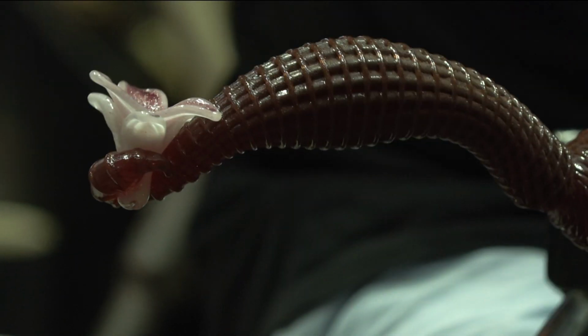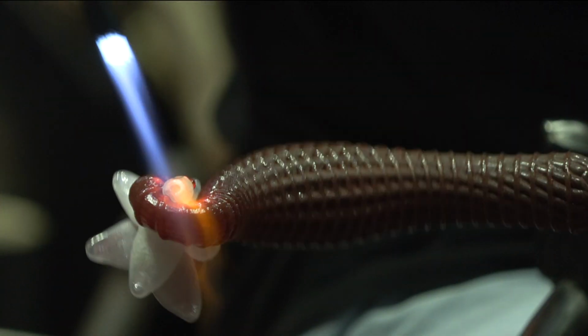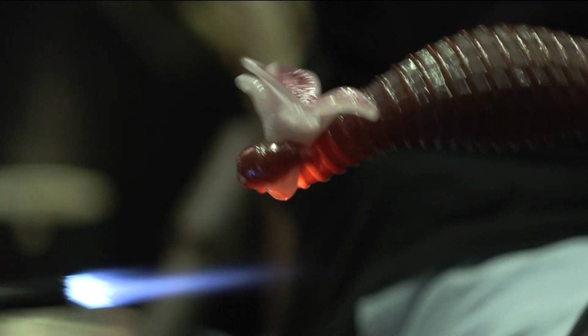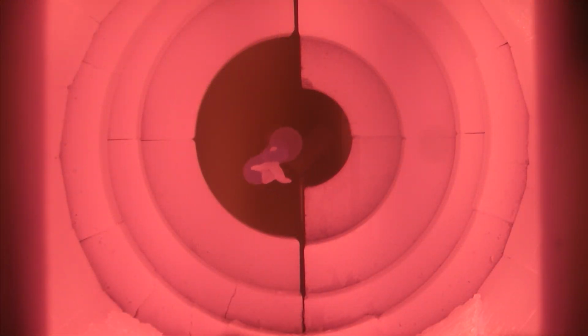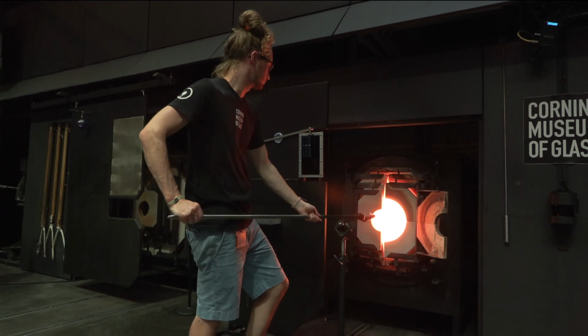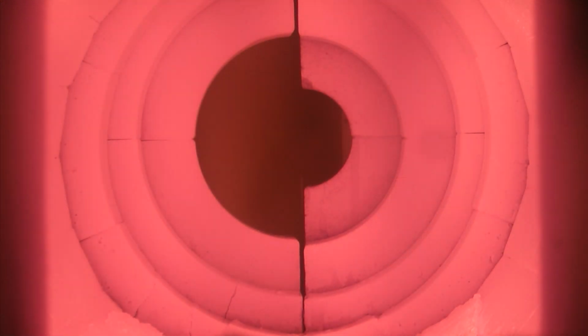And I was watching Chris make these flowers earlier, and if you look really carefully, they're kind of two different cones stuck together. These were originally two bubbles. So he blew a tiny little bubble, broke the tip open, and then cut into the sides of that bubble to flare open the petals. Then dropped a little extra pink color on the inside to give that lily-like effect. Once he had two of those little shapes, then we were able to stick those together to create that final flower. But a really, really lovely technique. It makes for really nice, even petals.